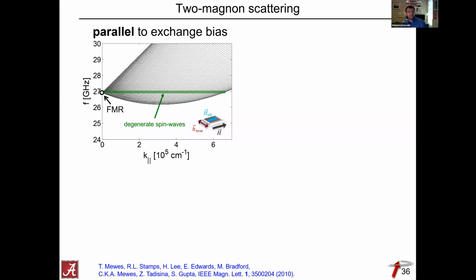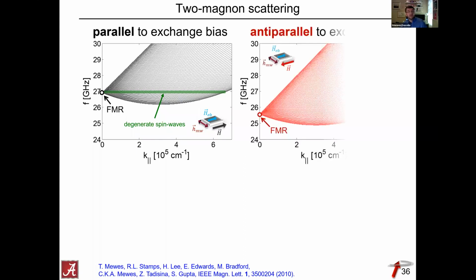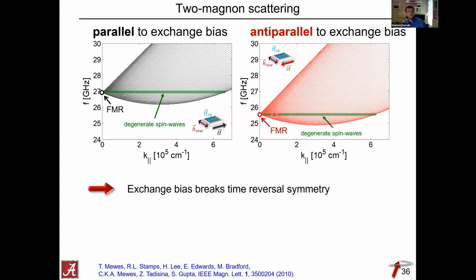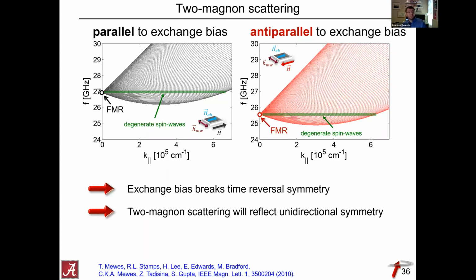So this is the configuration where we apply the field parallel to the bias direction. If you turn it around, you can already see that the manifold that you can scatter into differs from the parallel configuration, and you obviously can do this numerically. And so the bottom line here is, because exchange bias breaks the time reversal symmetry, you would expect that two magnon scattering will reflect this unidirectional anisotropy, or symmetry of the system. But the question is, well, is that all there is? Is it really just two magnon scattering?